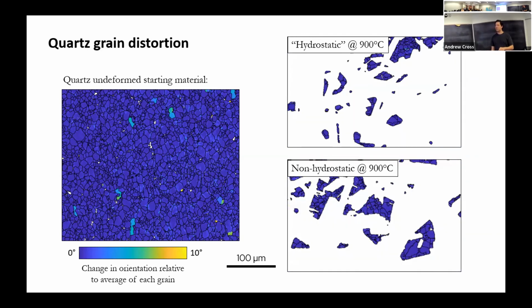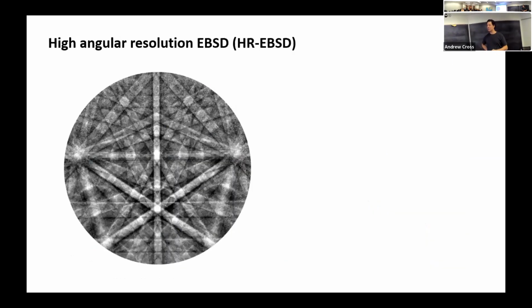So thinking about the quartz, we wondered if maybe we just didn't have the amount of precision that we needed with EBSD. Regular, bog standard EBSD will get you precision in terms of orientation down to about 0.5 degree. So something that we've been playing around with, and this is really work in progress, there's not too much that we've got to show for this yet. We just spent a week in Cambridge with Dave Wallace, who's really an expert in this high angular resolution EBSD technique.